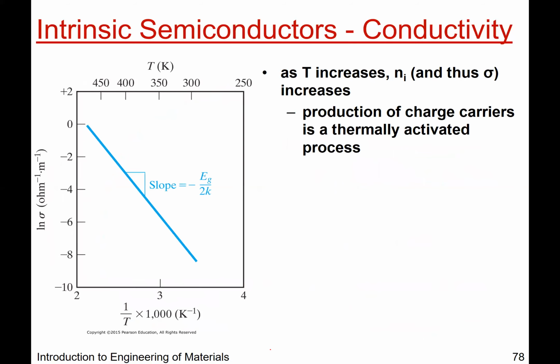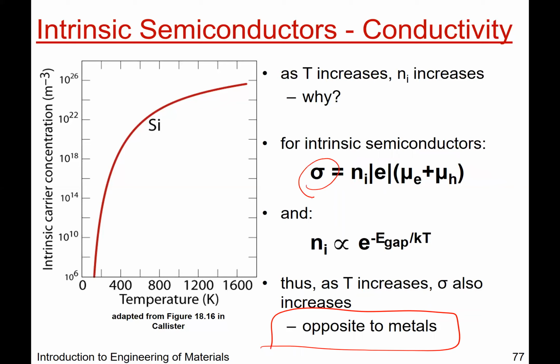And because it's an Arrhenius type relationship where it's thermally activated, we can backtrack and calculate the band gap of the material by measuring the conductivity, right? So let's go back. If you measure the conductivity, what's hidden in your conductivity are all these terms about carrier concentration and also mobilities of your electron and your hole.